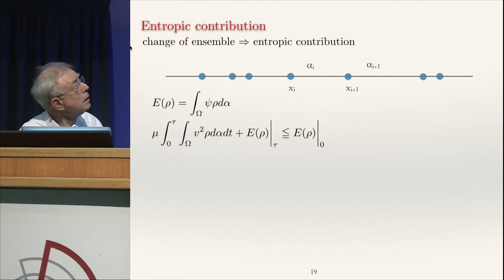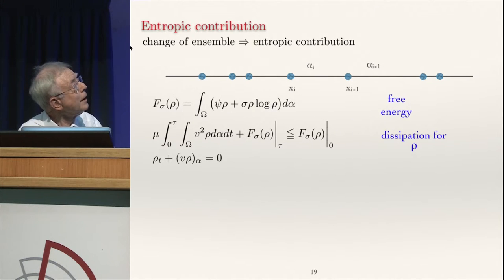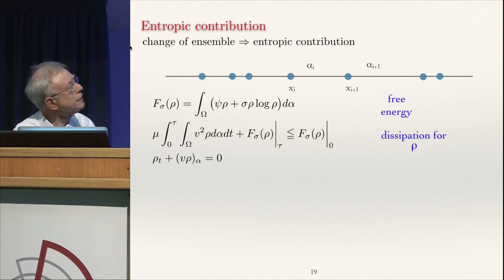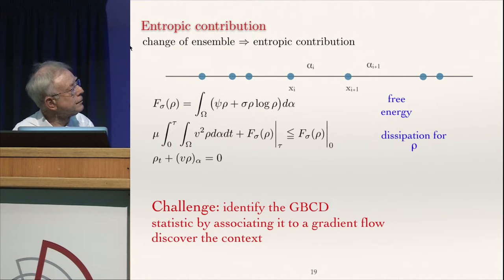So here is a new F instead of E, which has some simple entropy. This is the simplest entropy we could think of. And by the way, this development of this theory in the subsequent simulations, not the primary ones, but the subsequent ones, which you see, were done mostly with Katja Epstein, and she deserves a lot of credit for this, I think. So here is a free energy, and here is an expression, a dissipation equation for the energy at a given time tau versus the energy at some initial time zero, or some beginning to measure time zero. And the challenge now is to identify the GBCD statistic by associating it to a gradient flow, and we have to discover the context for this.